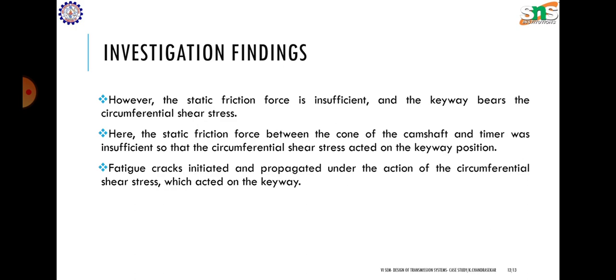Additionally, there is a general conception that a notch or sharp corner acts as a stress concentrator for cracks and leads to easy initiation of fatigue cracks. So it is suggested that fatigue cracks initiated and propagated under the action of circumferential shear stress, which acted at the keyway. So the appearance of abnormal Widmanstätten structure ferrite in the keyway region facilitated the cracking process. Okay.